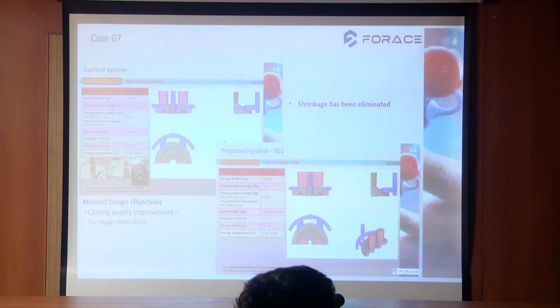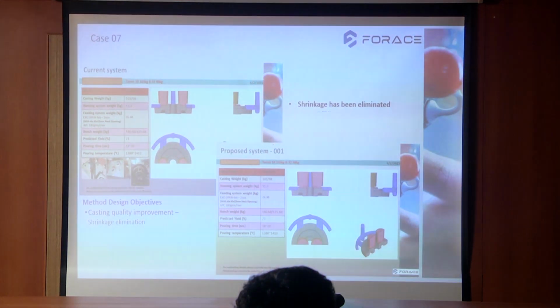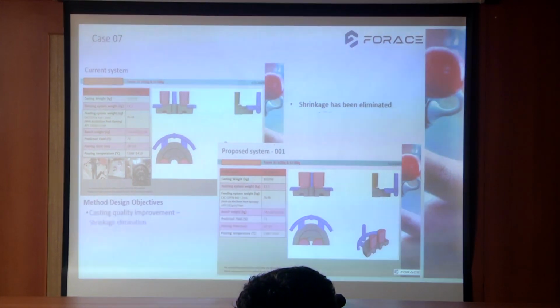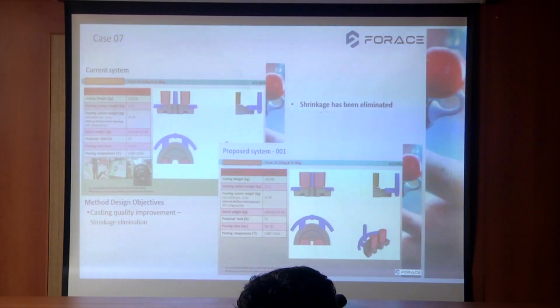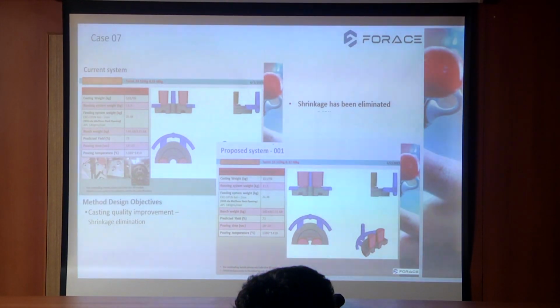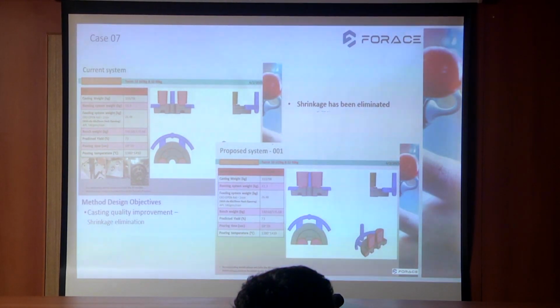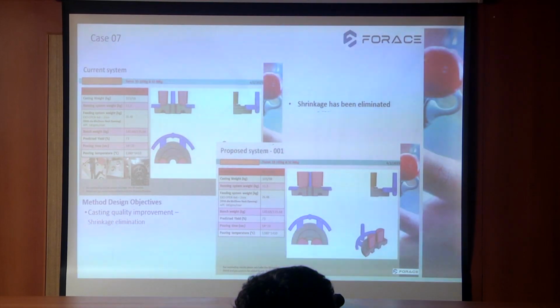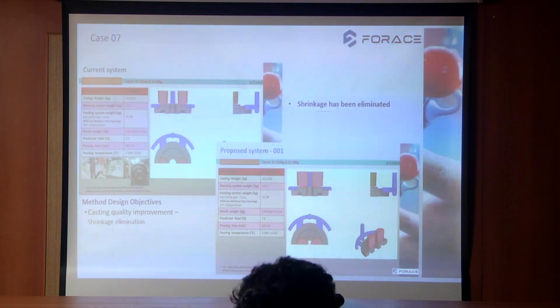So this is also a defect. They were getting some defects under the risers because of wrong selection or wrong placement of the sleeves. So we did the simulations and gave the proposals, and we adjusted the location of the sleeves so that the defect and the casting will be fed at the hotspot itself.